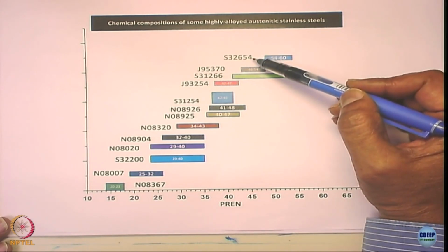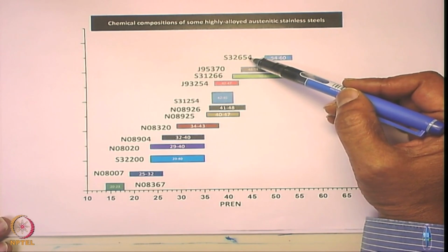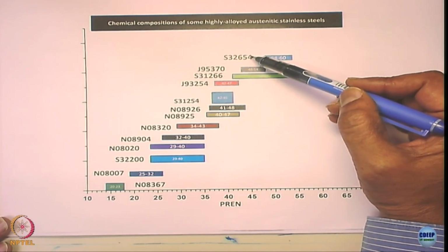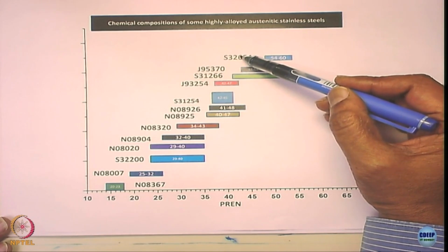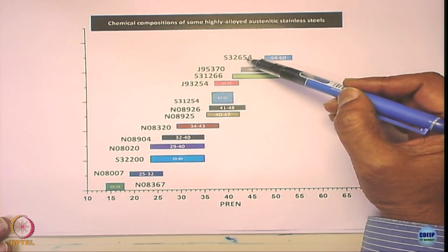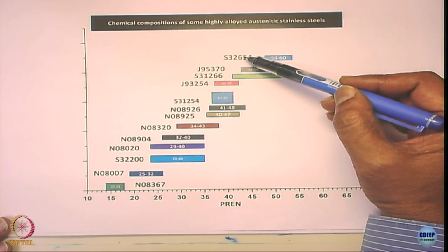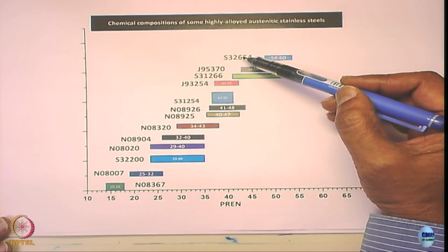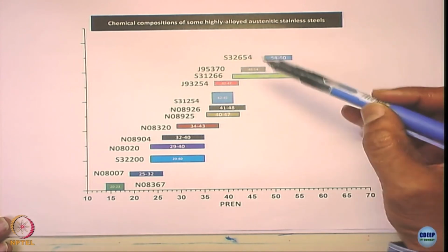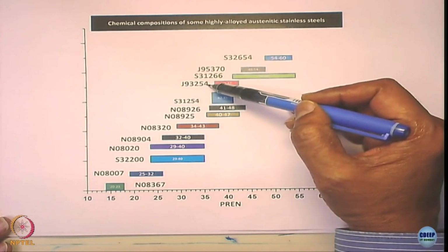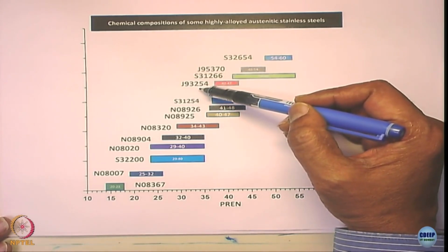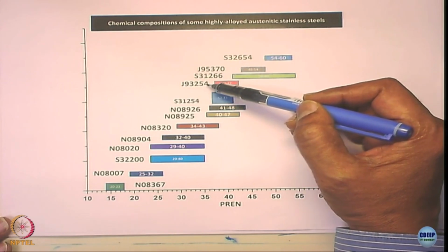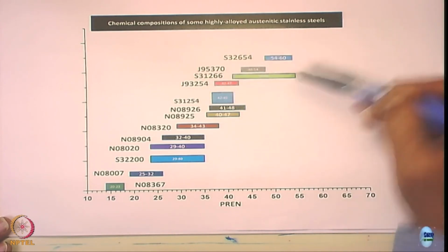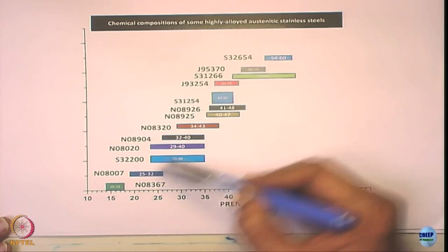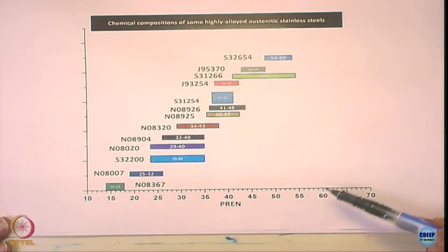This is called the 654 SMO, okay. This has 6 molybdenum, a higher amount of molybdenum is present here. Now you cannot add a high amount of molybdenum because it becomes a ferritic stabilizer, so people add more nickel to that actually. So you also have 254 SMO, and 25 chromium, and so various kinds of stainless steels are being developed in order to have